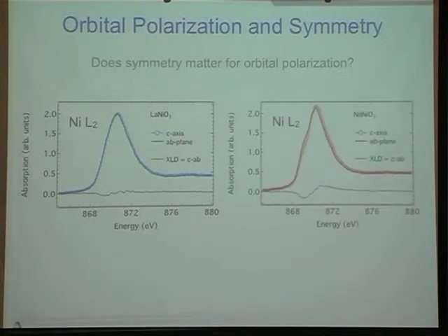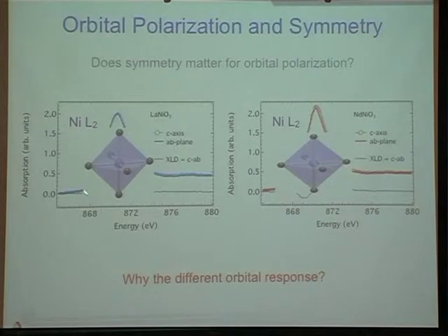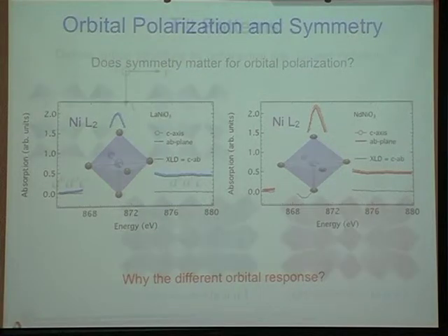However, if you do the same experiment in neodymium nickelate, which is under a very similar strain state, you see a clear difference between these 2 spectra, showing there is an orbital polarization. It's small, but there is a non-zero orbital polarization. So the big question is, it sounds like this octahedra is still regular. This octahedra is distorted. It's collapsed out of plane. So why the difference between these 2? From a pseudo-cubic perspective, they're very similar.